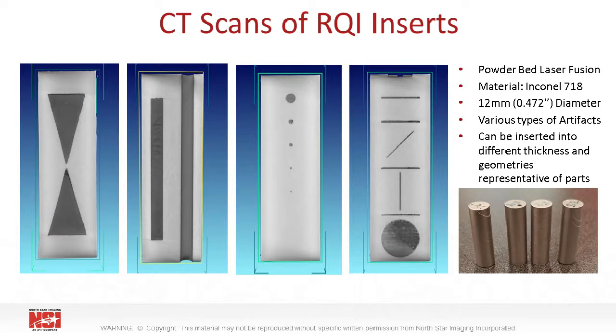The 2 inserts on the left can be configured to provide one chamber powder filled and the other chamber empty for comparison. The planar defect configurations on the right would represent larger diameter unfused powder defects with varying thicknesses and orientation. The varying size features allow for these inserts to be placed within really thick materials for high energy imaging also.